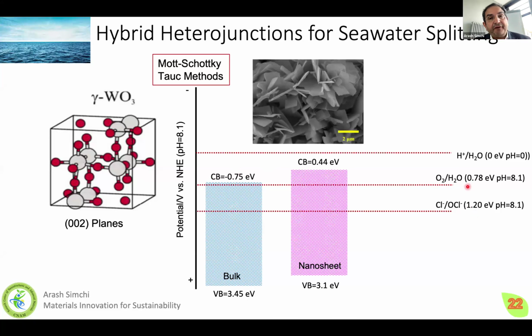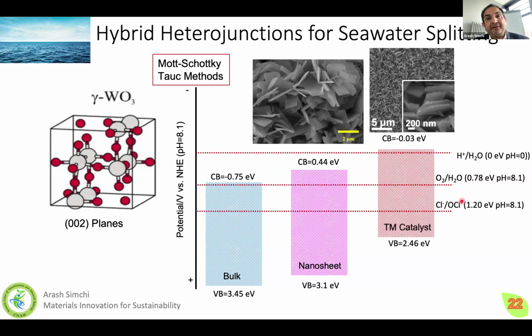What we are doing, if we use nanostructure, make it nanosheets instead of bulk tungsten oxide, now we have an upshift of the conduction band in a way that it makes it better, at least for water dissociation, but still we have a problem with the chlorine ions. The other system is to add a transition metal catalyst on the top, further upshift in a way that hydrogen reaction is feasible, while the chlorine reduction goes near the valence band, below the Fermi level, so it does not produce chlorine ions. This is the concept of our research.